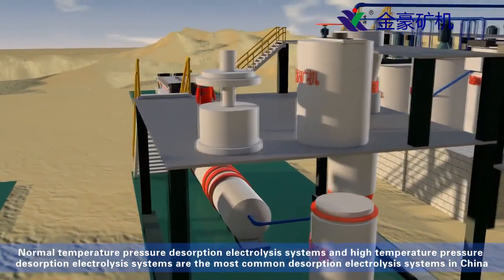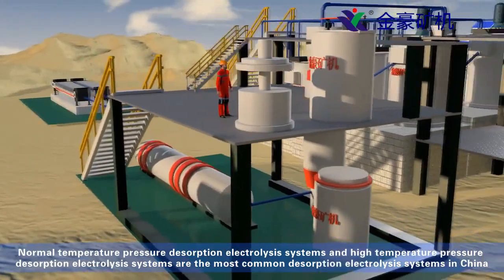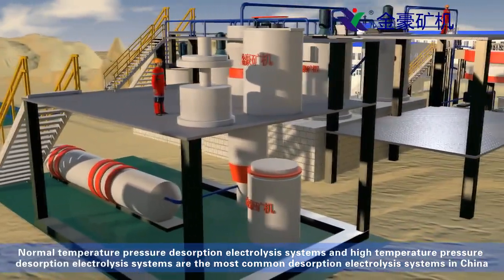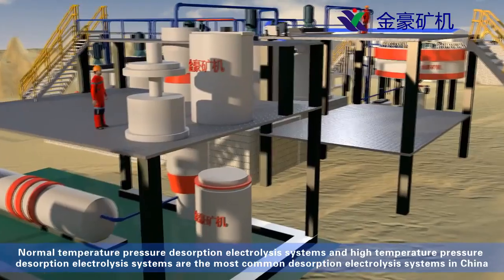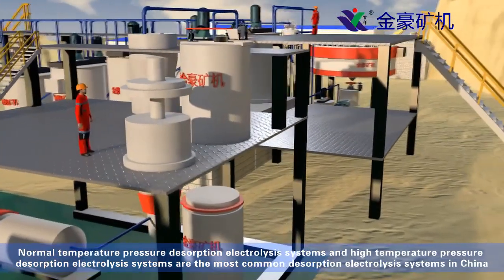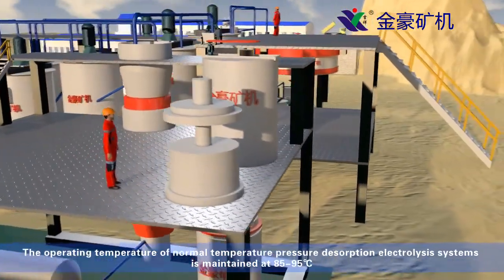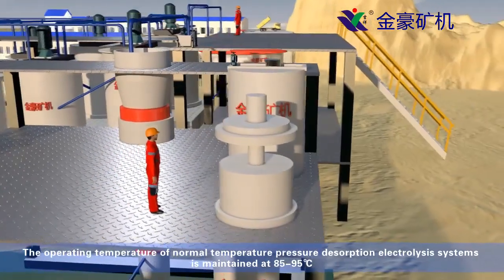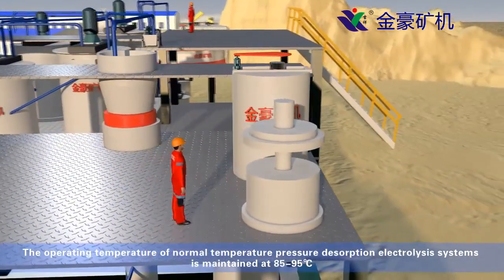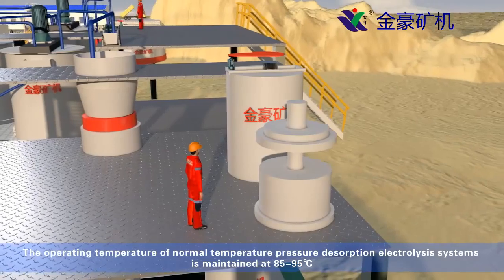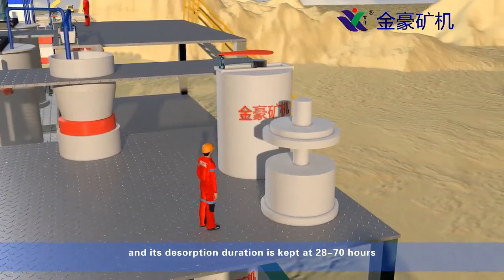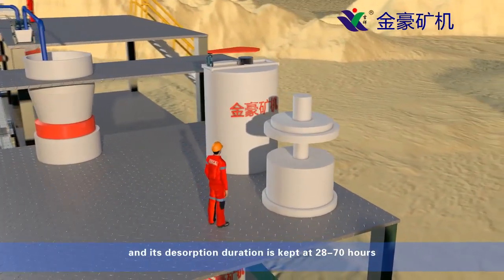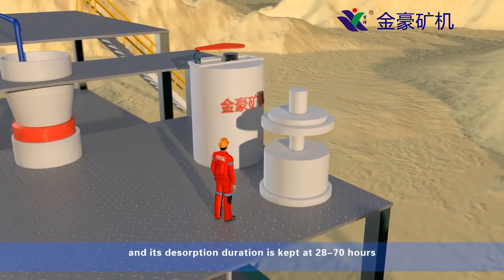Normal temperature pressure desorption electrolysis systems and high temperature pressure desorption electrolysis systems are the most common desorption electrolysis systems in China. The operating temperature of normal temperature pressure desorption electrolysis systems is maintained at 85 to 95 degrees Celsius, and its desorption duration is kept at 28 to 70 hours.